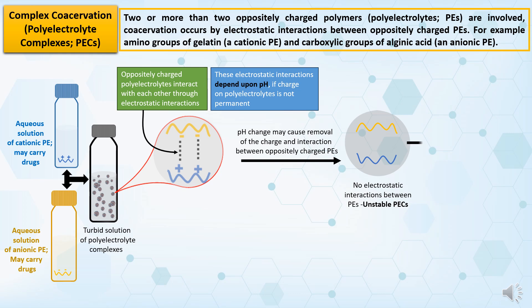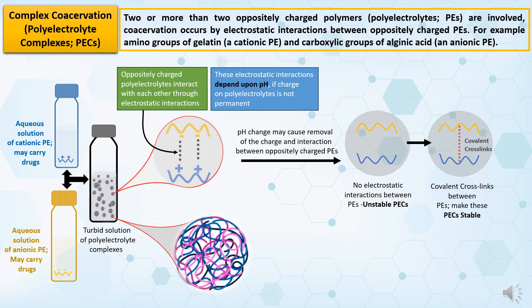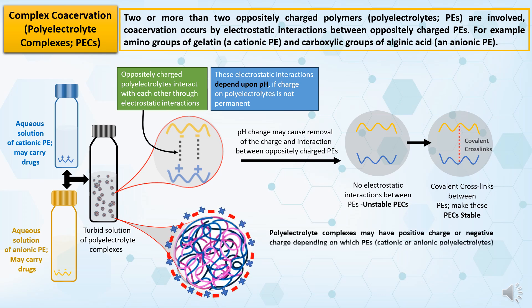This problem of pH instability can be overcome by adding crosslinking agents, which make covalent crosslinks between oppositely charged polyelectrolytes. The obtained polyelectrolyte complexes may have a net positive or negative charge on their surface, depending on whether the cationic or anionic polyelectrolyte is used in excess.